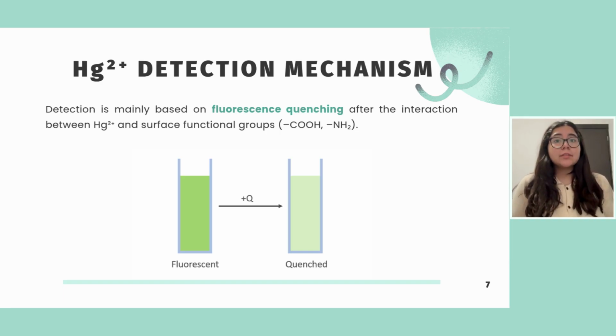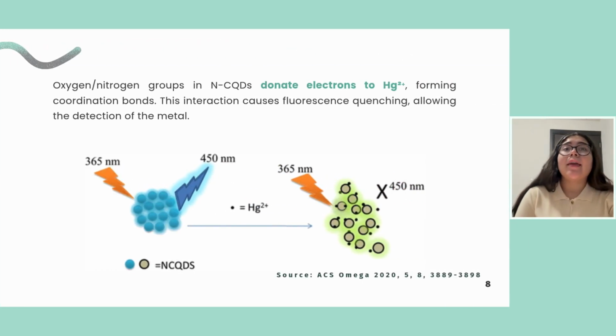But how do carbon quantum dots detect mercury? Well, several studies have demonstrated the effectiveness of carbon quantum dots for mercury-2 ion sensing through a fluorescence quenching mechanism. This phenomenon occurs due to the interaction between mercury-2 ions and the functional groups present on the carbon quantum dot surface, particularly carboxylic groups, which facilitate electron transfer and suppress fluorescence emission. According to Teruel and collaborators, the sensing mechanism of nitrogen-doped carbon quantum dots is based on the interaction between oxygen and nitrogen-containing functional groups and mercury-2 cations.